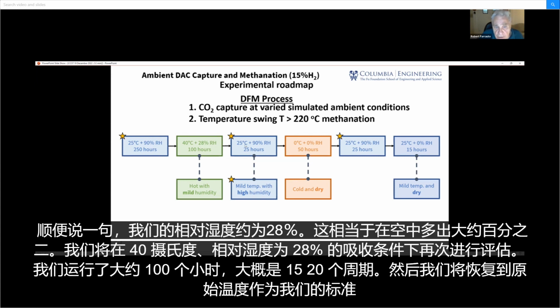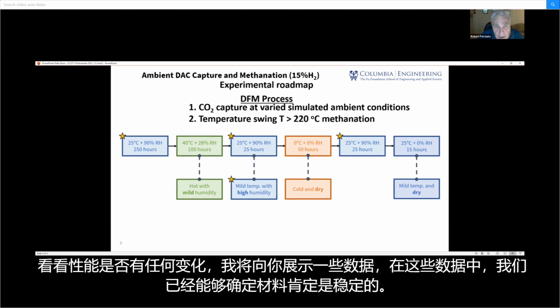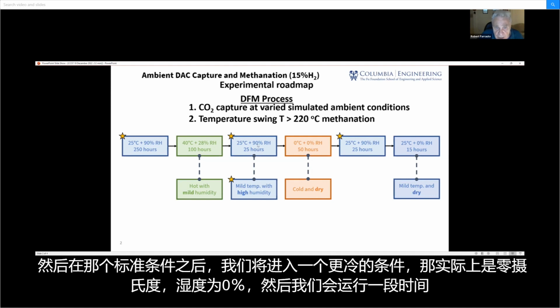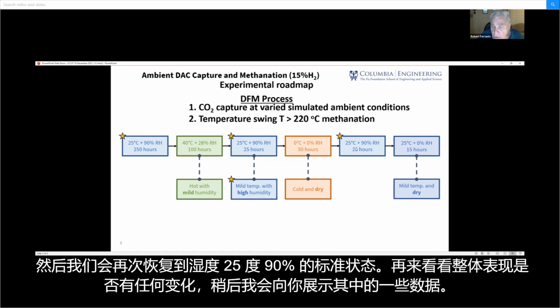And then we would return to our original temperature as our standard to see whether or not there's been any change in the performance. And I'll show you some data where we've been able to establish that the material is certainly stable. And then after that standard condition, we would then go to a colder condition, which would be effectively 0 degrees centigrade with 0% humidity. And we would operate for a certain length of time. And then we would again return back to effectively our standard condition of 25 degrees, 90% humidity, again, to see whether or not there's been any change in the overall performance. And I'll show you some of that data in a moment.